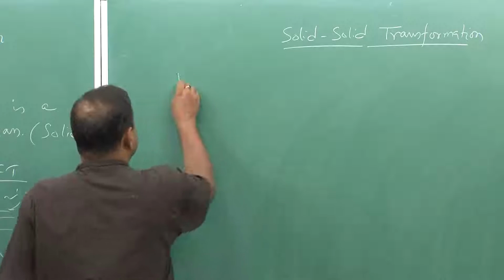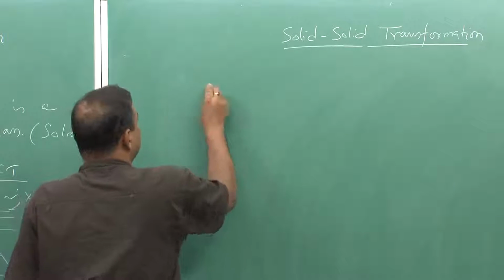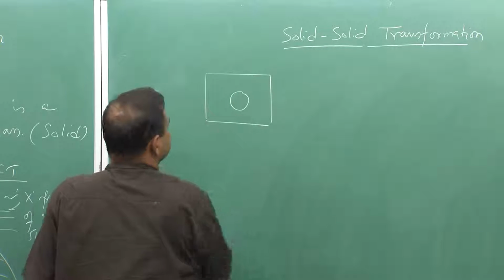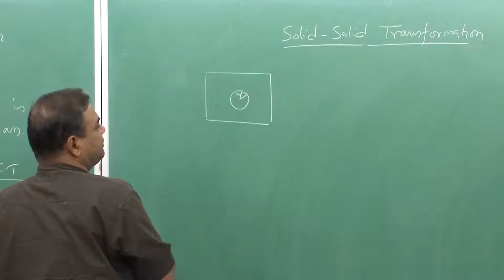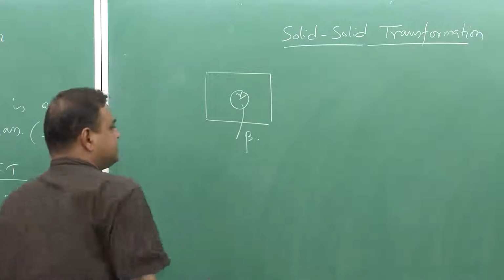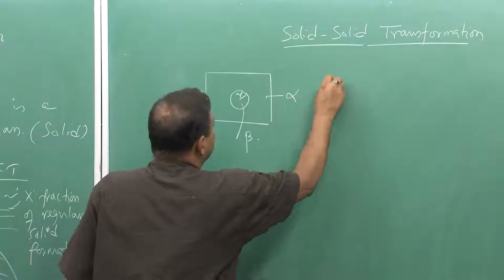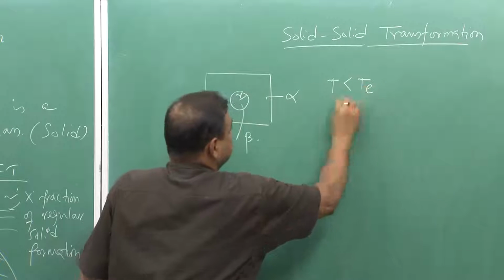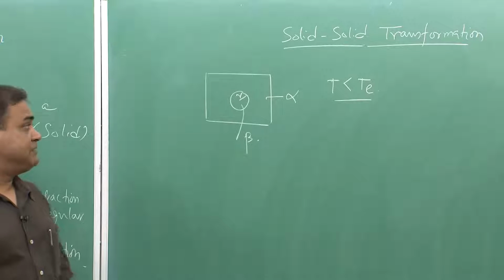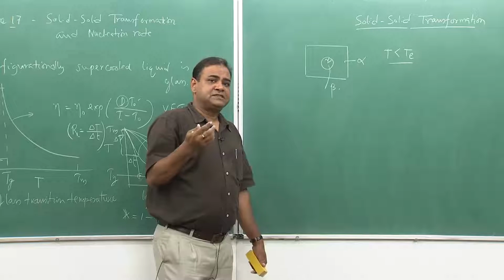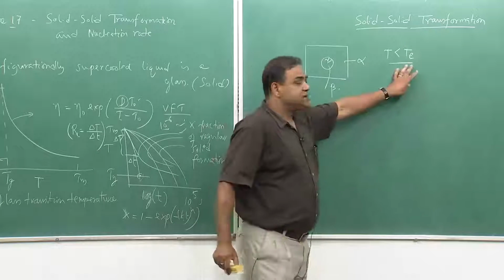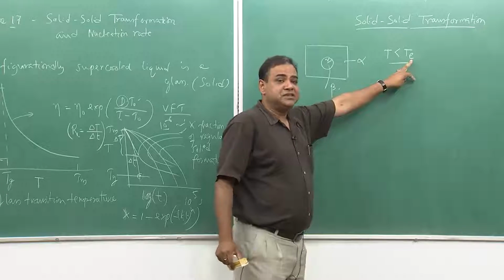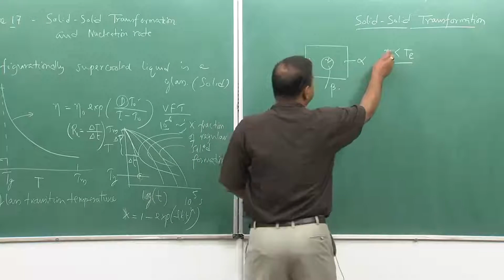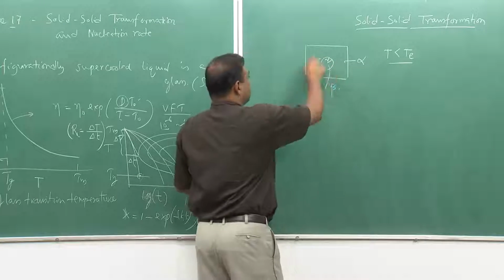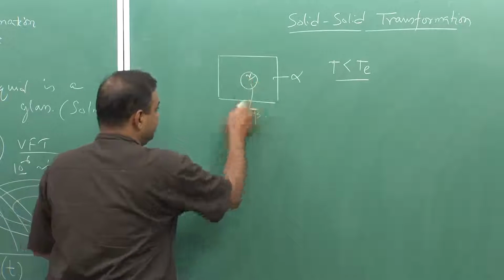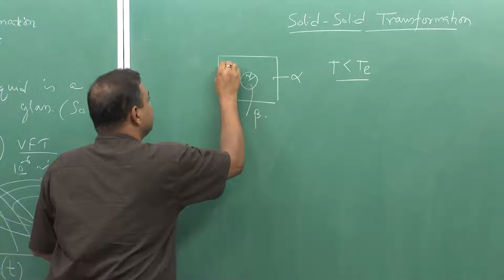Now, in case of solid transformation, of course, initially we can see homogeneous nucleation. So they are also spheres of radius r, and that solid, let me term it as beta, is forming in alpha at a temperature less than the equilibrium temperature. So I am here putting not Tm, it is rather the equilibrium temperature. Tm is also an equilibrium temperature, but since it was melting, that is what we called Tm, but here the transformation equilibrium temperature is Te. Now, at this temperature which is less than Te, the transformation is taking place, where beta is forming in a solid of alpha, and the interface which is forming is gamma alpha beta.